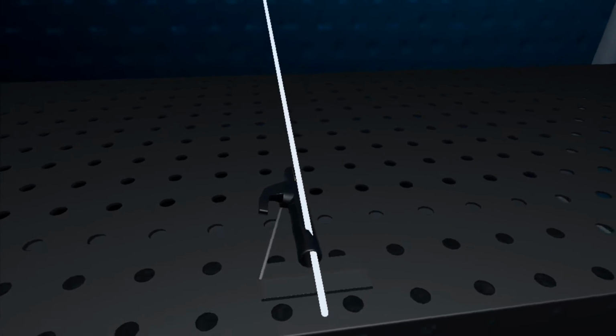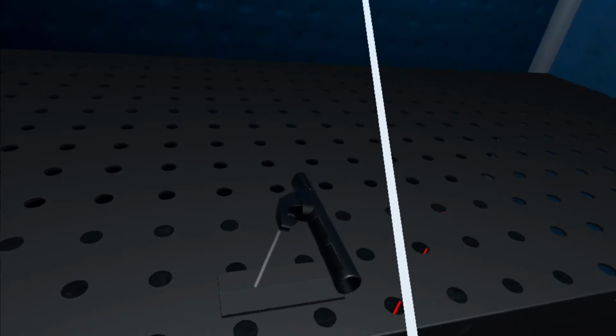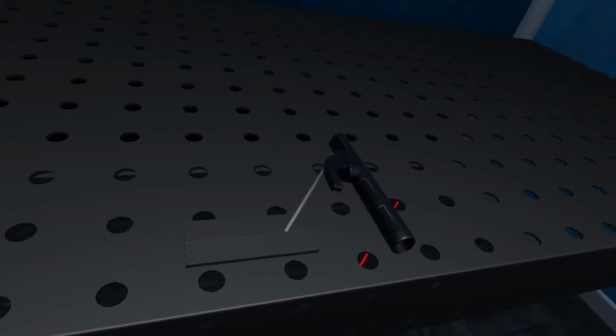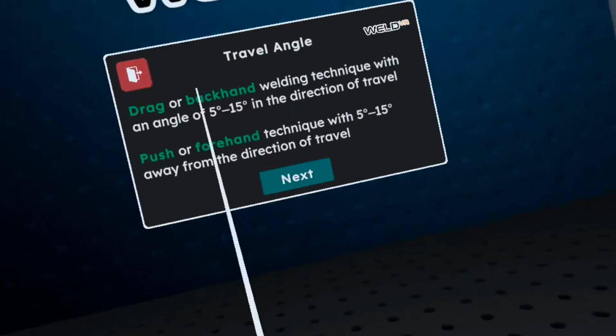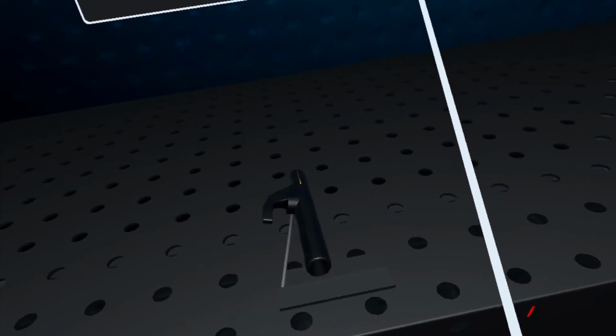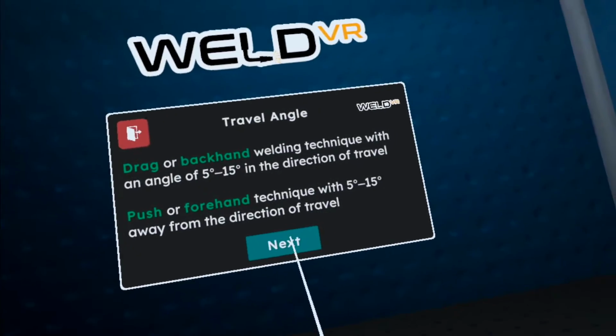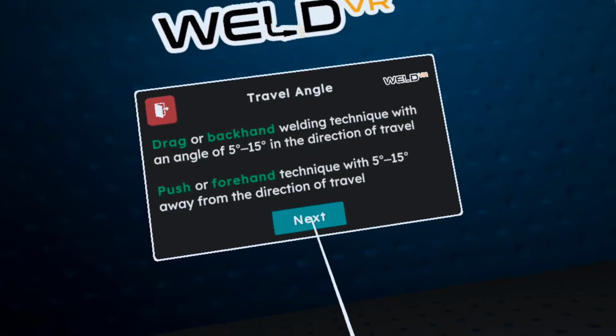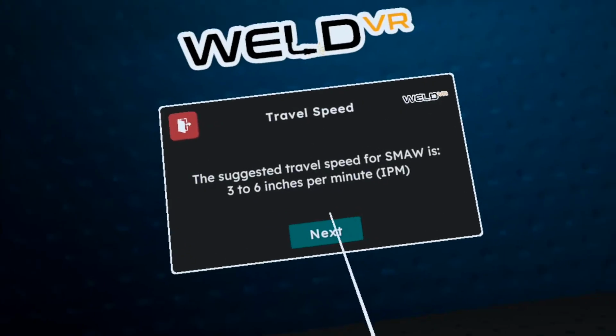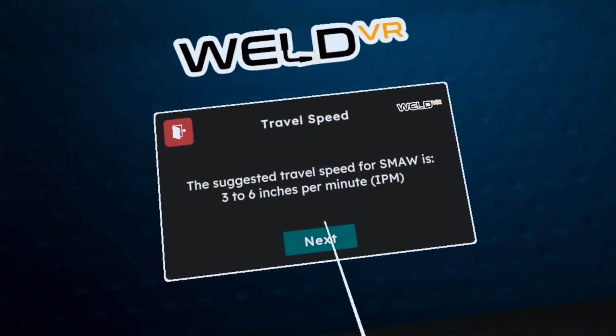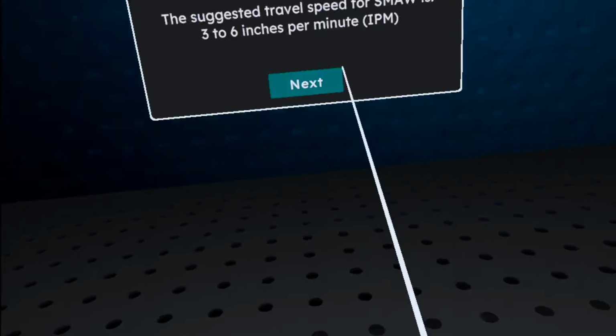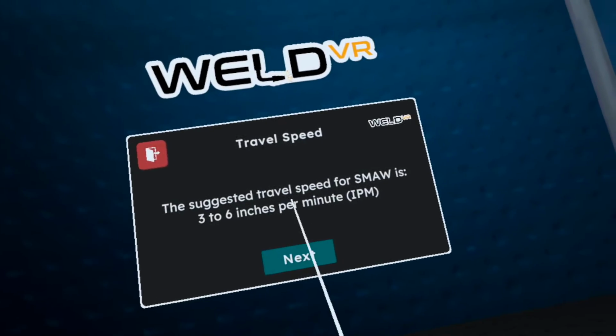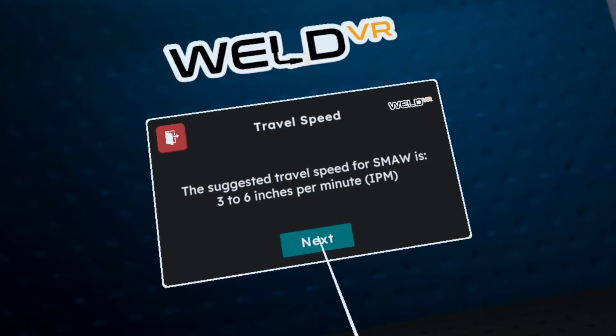Stick welding in the flat, horizontal, and overhead positions uses a drag or backhand welding technique. Hold the electrode perpendicular to the joint, and then tilt the top in the direction of travel approximately 5 to 15 degrees. Traveling too slowly produces a wide convex bead with shallow penetration. Excessively fast travel speeds also decrease penetration, and create a narrower and/or highly crowned bead.